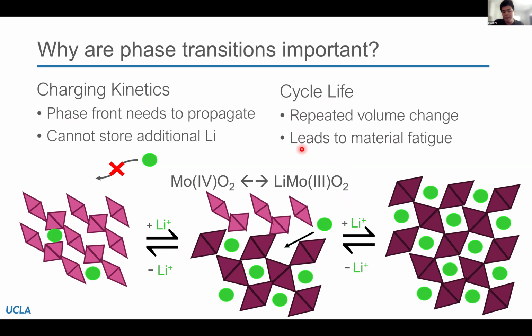And so this can be understood because we have a near instantaneous volume change of our material, which causes a lot of strain on the particle level. And so over many cycles, you can begin to crack or even destroy your particles. So that's one of the main reasons why, when you use a battery over and over again, you can't get as much energy out of it over time.